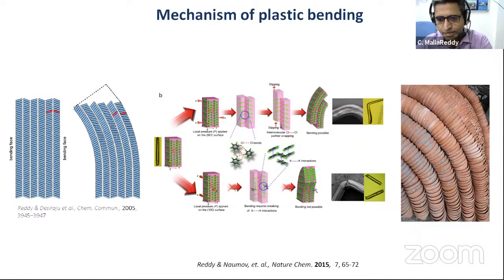So then again, we try to do nano indentation. We have done the diffraction studies using the microfocus synchrotron, and we see that there is not a big change in the lattice parameters. There is some change, but it's not a big change. And more or less, it confirms that the model that we proposed, in general terms, it follows, and that is what we proposed using synchrotron studies here.